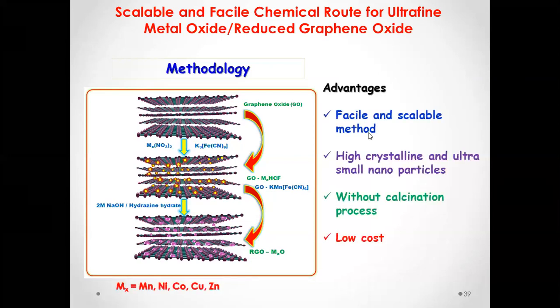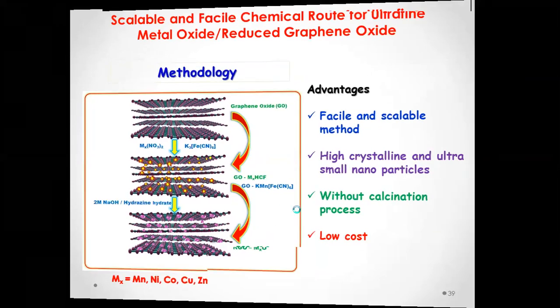So that's why this process is very facile and scalable for large scale preparation. More importantly, without any heat treatment, we are able to make a crystalline compound, also in the nano size range. This process is also very low cost. Since it's only a two-step process, you can end up with a crystalline metal oxide decoration on the graphene sheets. So because of this, performance is also very high. We have demonstrated this for several metal oxides: manganese oxide, nickel oxide, cobalt oxide, copper oxide, and zinc oxide decorated graphene sheets. If some of you are interested, maybe you can just get it.